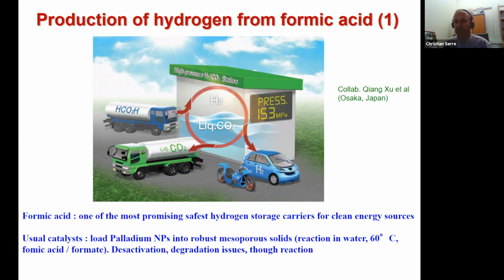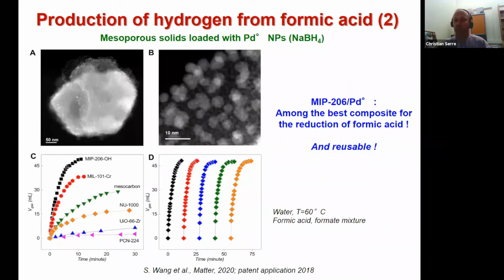The thing is that you need to transform it back to hydrogen if you want to utilize it. The state-of-the-art catalysts are palladium nanoparticles that are usually immobilized in mesoporous solids. But as the conditions are quite harsh, in water at 60 degrees Celsius, you need formic acid, formate, then there are a lot of deactivation and degradation issues with the mesoporous solid. So what they did is they took our solids and loaded them with palladium nanoparticles using sodium borohydride at 0 degrees Celsius. You can see on this figure that we have nanoparticles of a few nanometers in the MOF particles that are bigger, a few hundred nanometers.